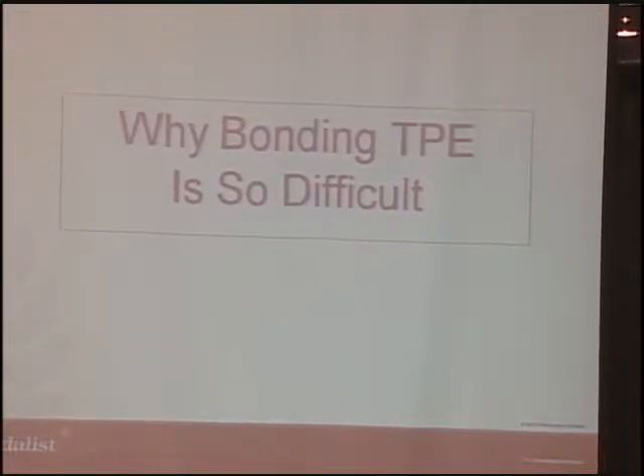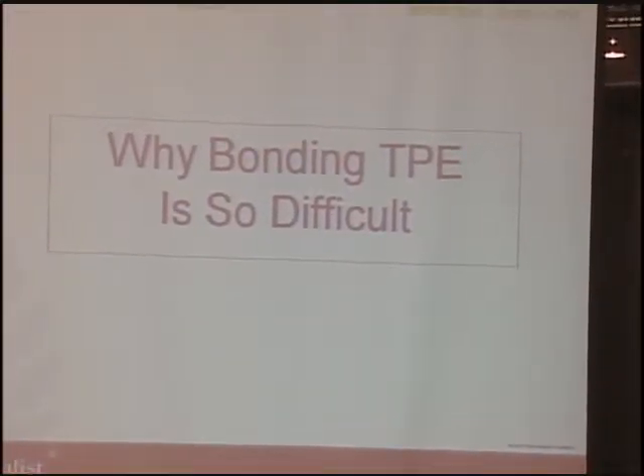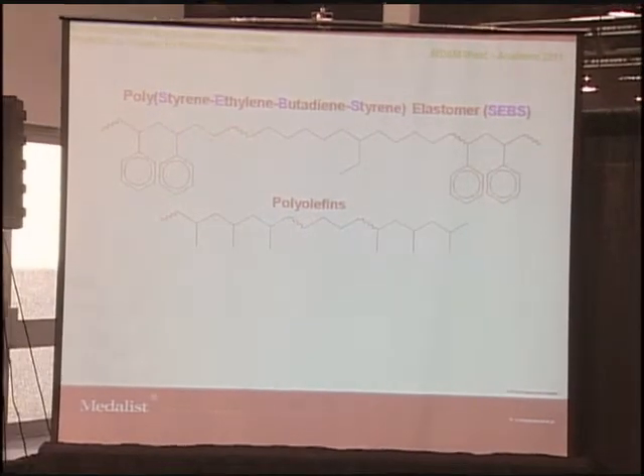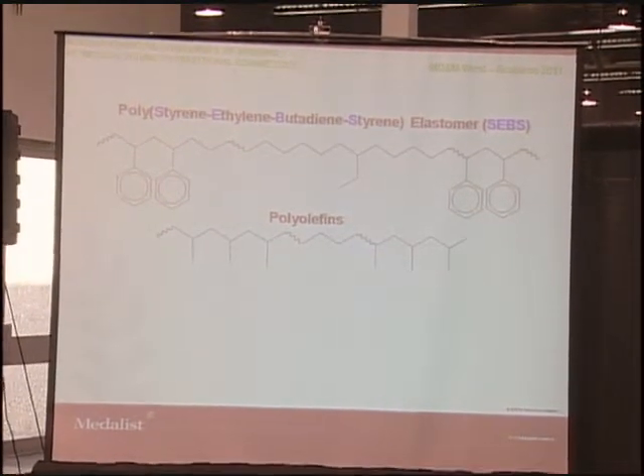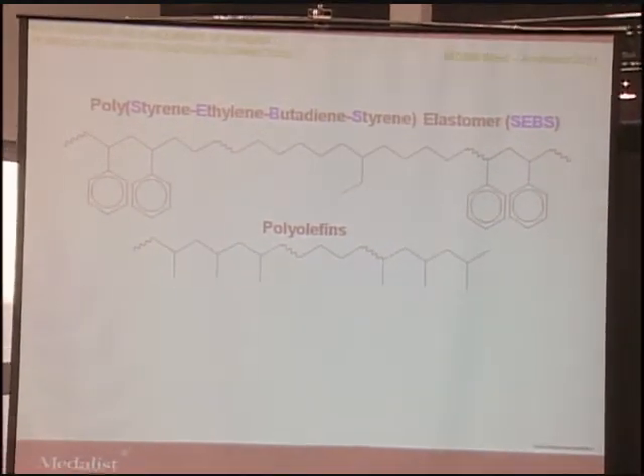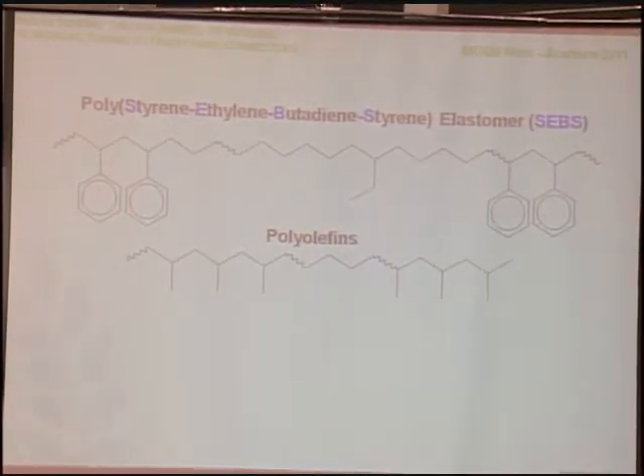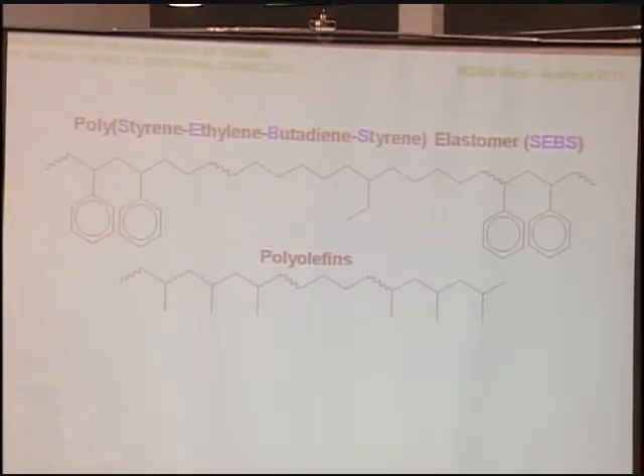So let's look into why bonding TPE is so difficult. This is the structure of the thermoplastic TPE based on SEBS elastomer and polyolefin. Those two polymers are very inert. The surface has very low surface energy, and they are not easily soluble in common solvents at room temperature. In fact, you can't really find a good solvent to dissolve them at room temperature.